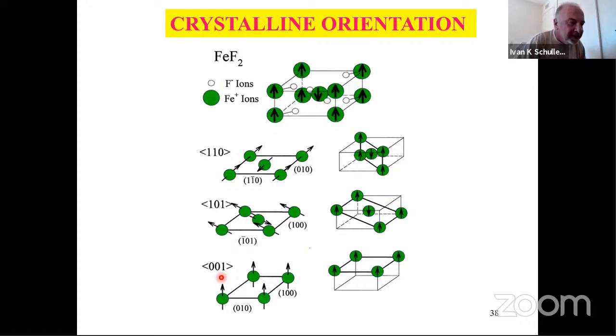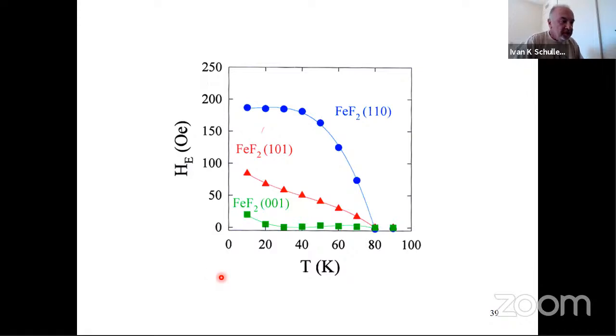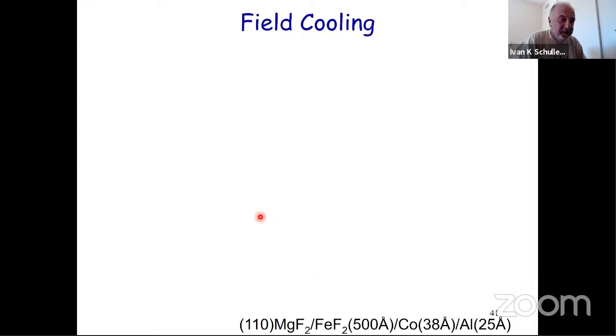And let me just show you what the result of the exchange bias of this system is. So here it is, the exchange bias as a function of temperature for the 110 and the 001, never mind the 101, that's the same. The fully uncompensated surface has the maximum exchange bias. And the fully compensated surface has zero exchange bias. Totally unexpected. And this was totally crazy to do, because I was told that we shouldn't be doing this.